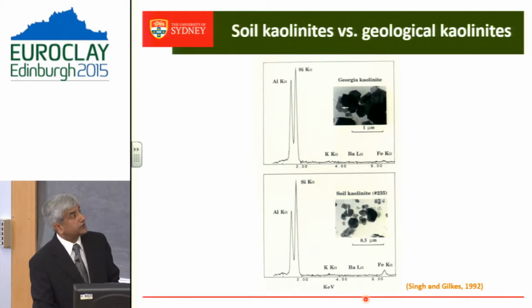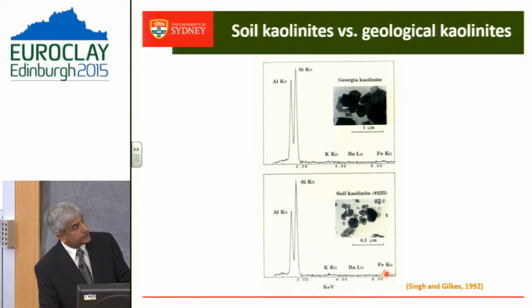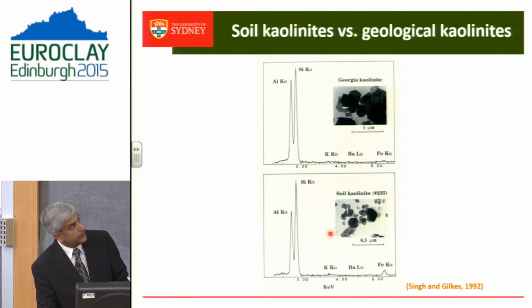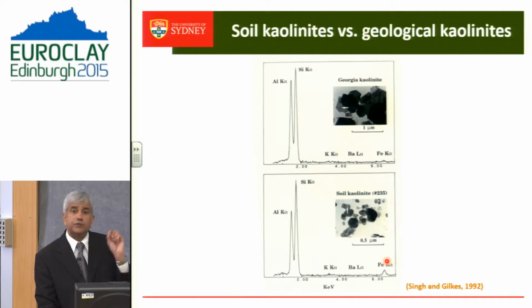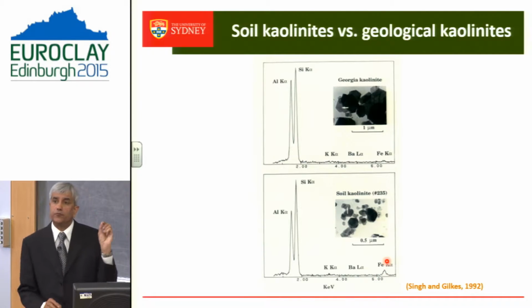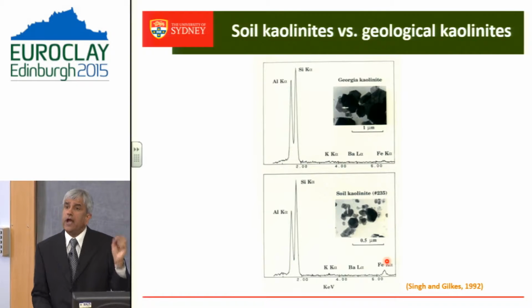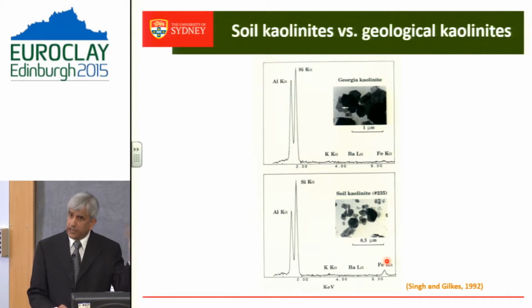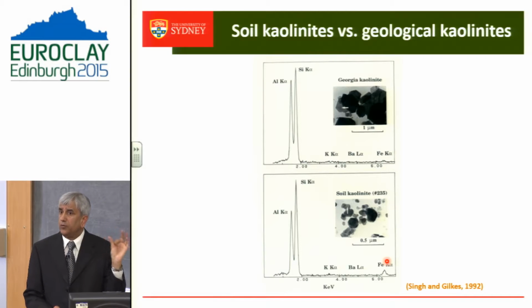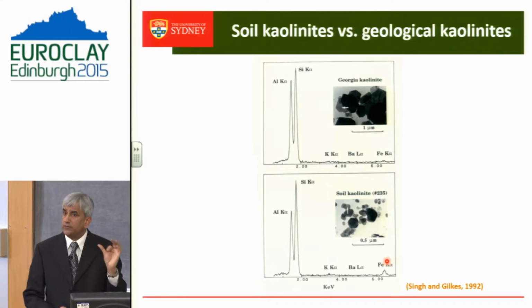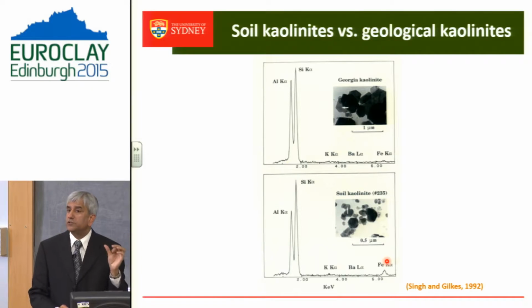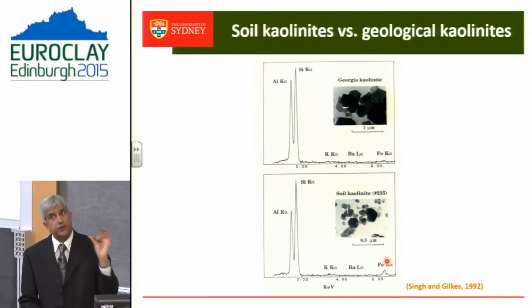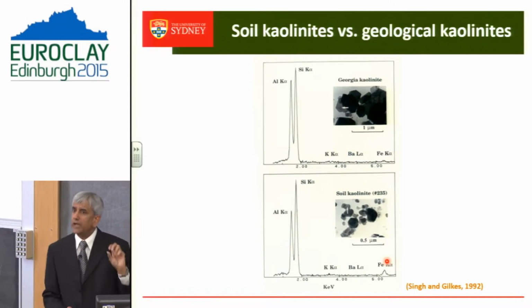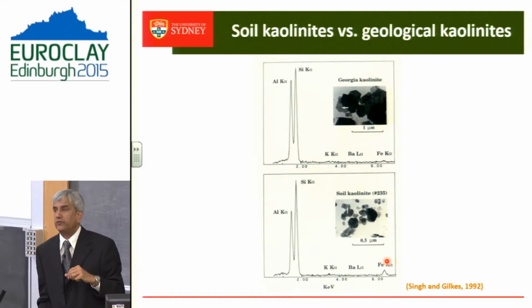There is iron in the structure of these kaolinite, as shown here from the single crystal microscopy. A lot of these soil kaolinites have up to 2.5 mole% of iron in the structure. And that iron, we have seen, is mostly an iron 3 form in the octahedral sheet, but a small amount could also be in the tetrahedral sheet, or in reduced form, iron 2, that might contribute a tiny amount of permanent charge in the structure.